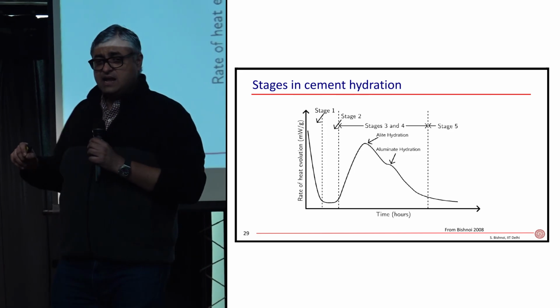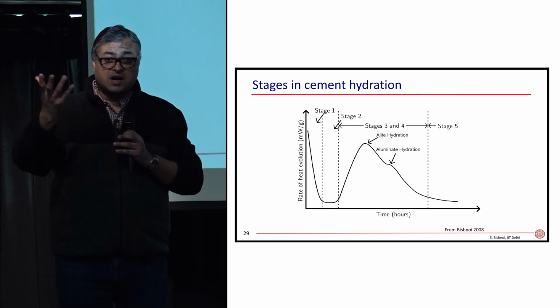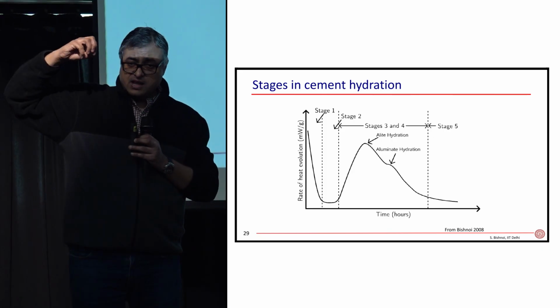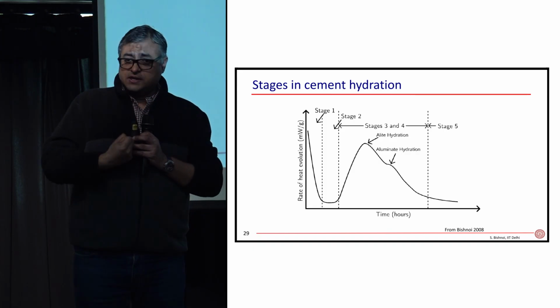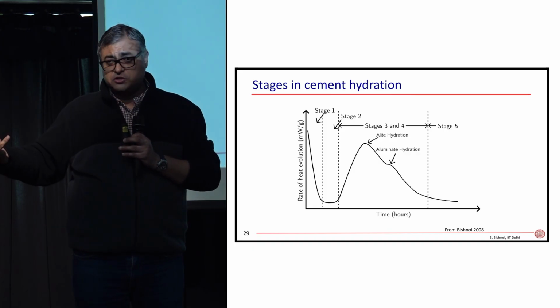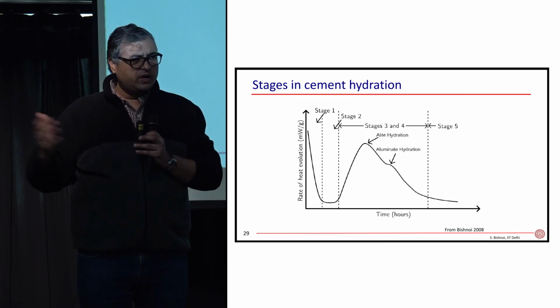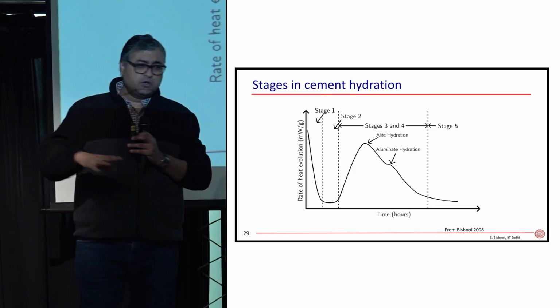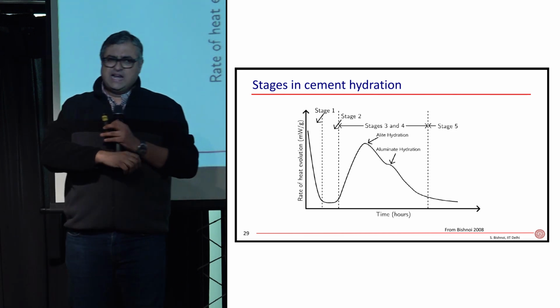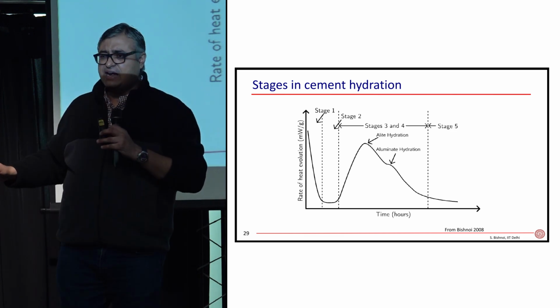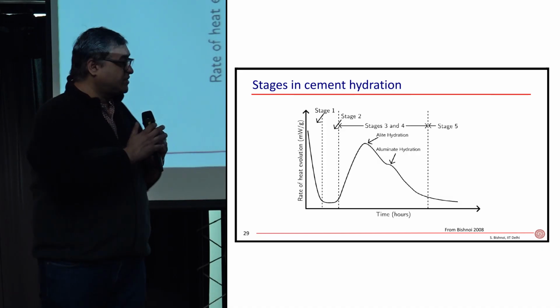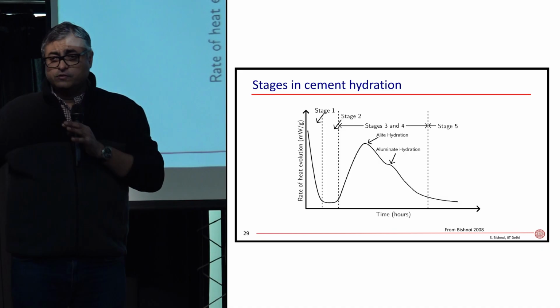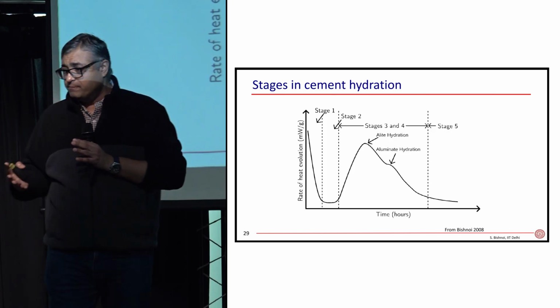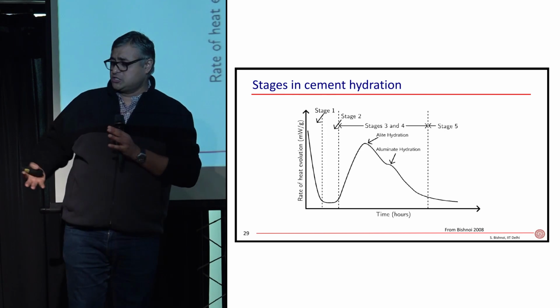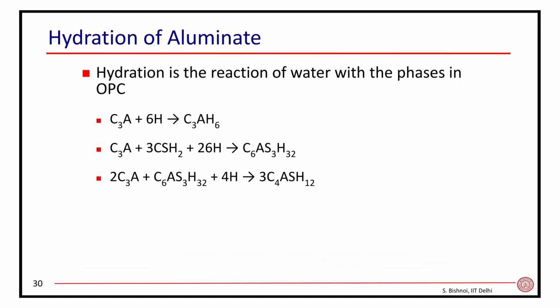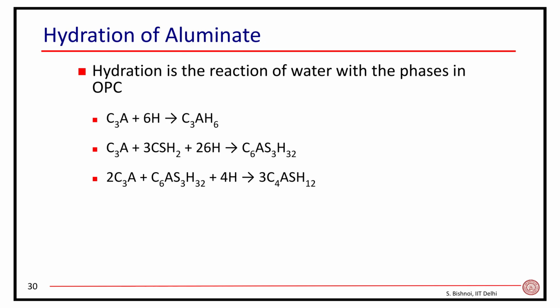Now your cement in the beginning is like a dispersion of particles. It's like a solution. You put the cement in, things dissolve, the materials go into the solution, the ions go into the solution. The ions from C3S, from C2S, from C3A, everything, the gypsum that you've added, they go into the solution, they keep colliding with each other and do whatever reaction that they can with the other material, which is why you end up with such a messy system, because all of those things are trying to react at the same time. And something reacts faster, something reacts slower, something happens first, something happens later, and that's why you get these bumps. What is it that happens first?